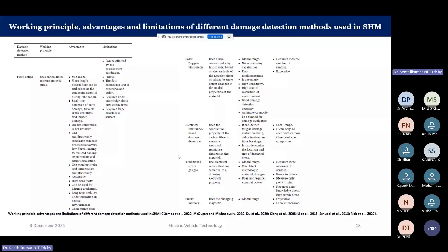So then many methods like this, there are like laser Doppler vibrometer, then electrical resistance based damage detection. So this is also conventionally people are using. It uses the conductive property of the carbon fibers to measure electrical resistance changes in the material. So it can detect the fatigue damage, matrix cracking, delamination, and fiber breakage. It can determine the location and the size of the damaged areas. So the limitation is the local range, and it can only be used with the carbon fiber reinforced composites.